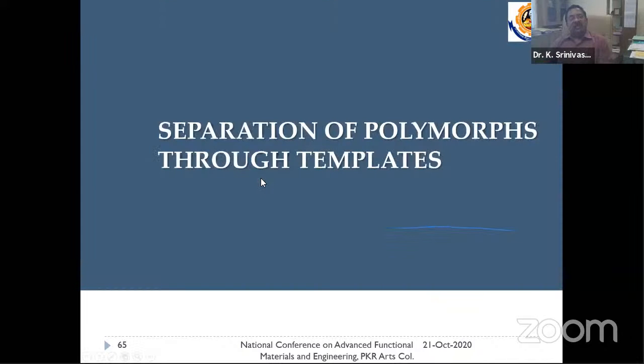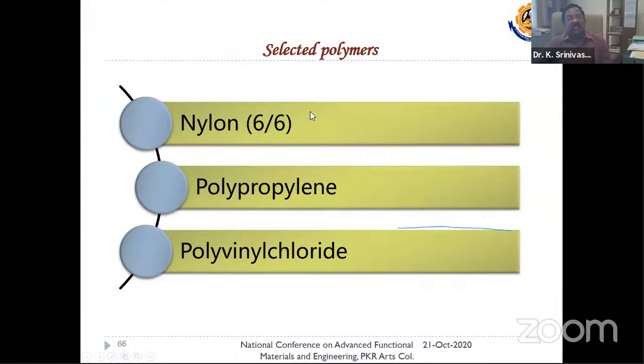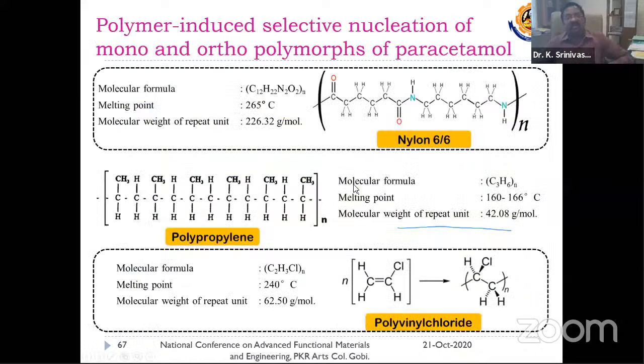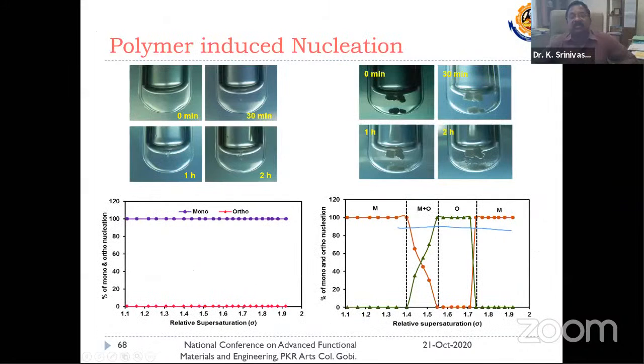And another technique we employed here is employing some templates. We deliberately inserted templates of polymers of different types into the solution, because here the nylon 6,6 or polypropylene or PVC, they have different molecular structures, you know. They are non-reactive with respect to this paracetamol solution. But when we introduce them, we are able to nucleate the desired polymorph. That was our success here.